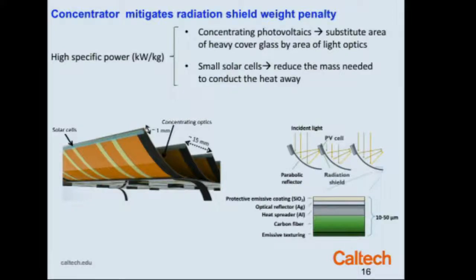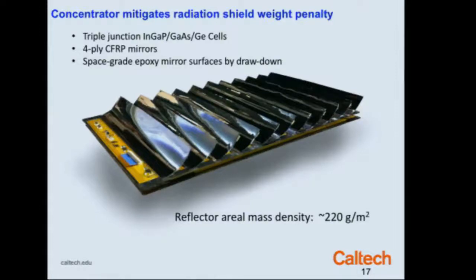The structure of the mirror consists of a number of optical coatings that are used to emit efficiently into the cold background of space and to reflect visible light efficiently onto the photovoltaic. I showed you the tile, and these structures have a mass density of 220 grams per square meter. It's a pretty lightweight structure. That's about the same weight per unit area as a number 10 envelope or so. Maybe with a letter inside. But that's about the mass density of the structure.